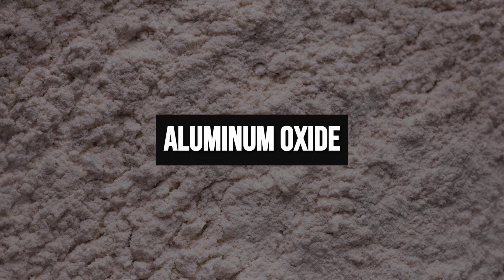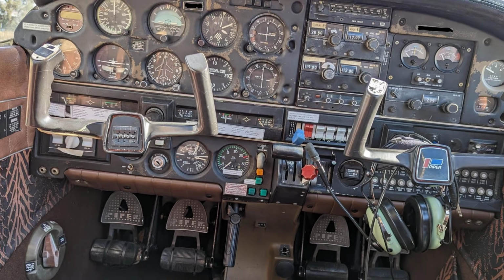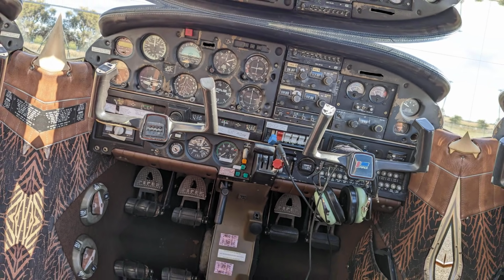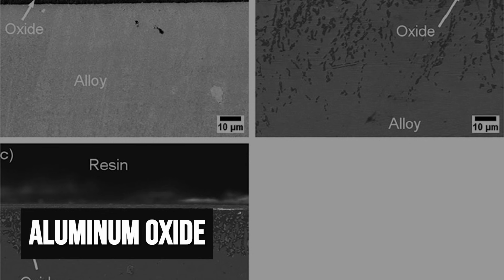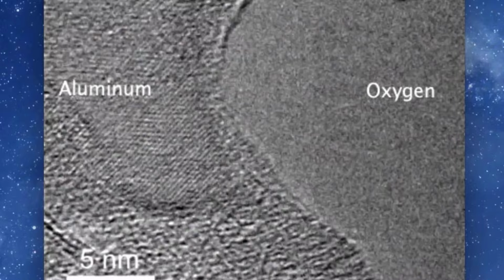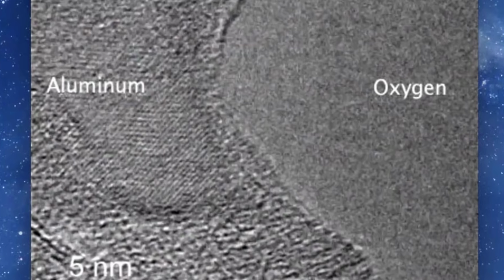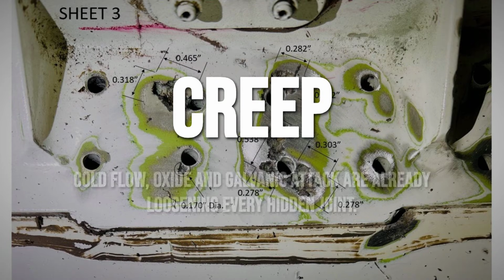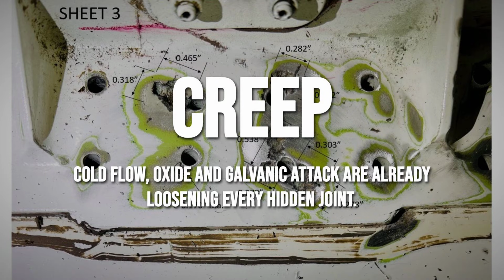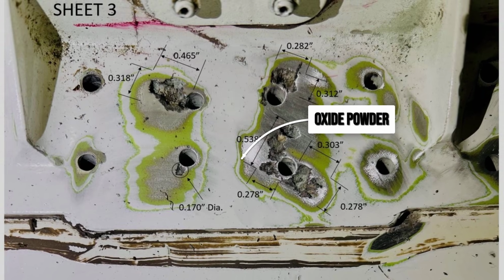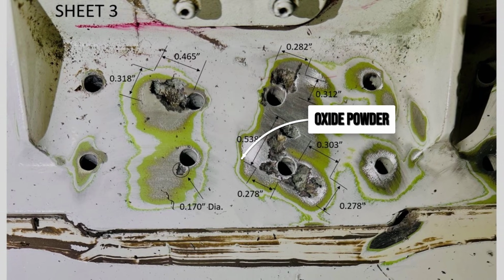Then comes the oxide. The moment aluminum is exposed to air, a thin skin of aluminum oxide forms, just a few nanometers at first, but it thickens over years, especially in a humid cockpit. The oxide is an insulator, not a conductor. Under a microscope, it appears as a dull, gray film, sometimes flecked with green or white powder, the so-called green death. The technician scrapes a terminal and finds the powder crumbling between the threads.